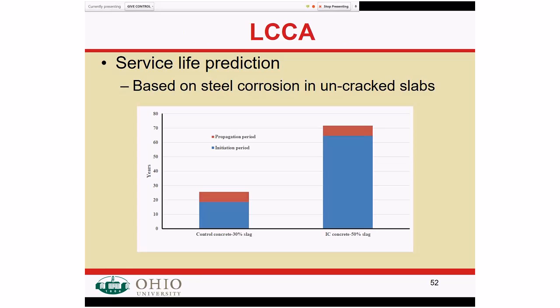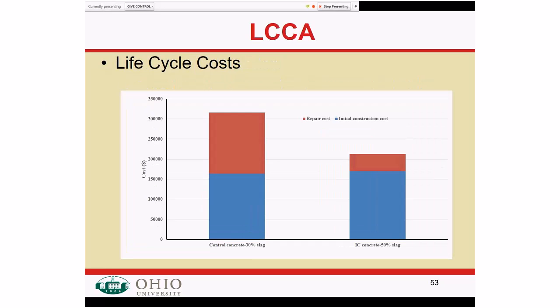And so we did a life cycle cost assessment. And what we found, based on the permeability data we've collected, and this was done using Life-365, is that for the initiation of corrosion of the reinforcing steel, we more than doubled, if not trebled, the time it will take for corrosion to initiate on the reinforcing steel. The propagation has been slowed a little bit, but if it means we can buy an extra 40 years out of the system, that's not trivial.